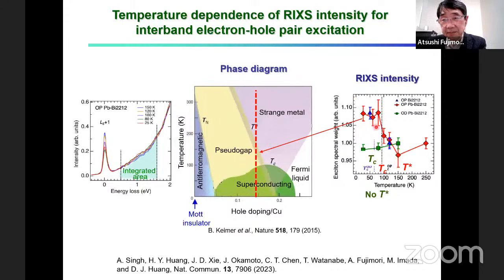As a function of temperature, this intensity increases below TC and is suppressed above T star. And for the overdoped sample, there is no pseudo gap state, so the intensity doesn't change as a function of temperature.